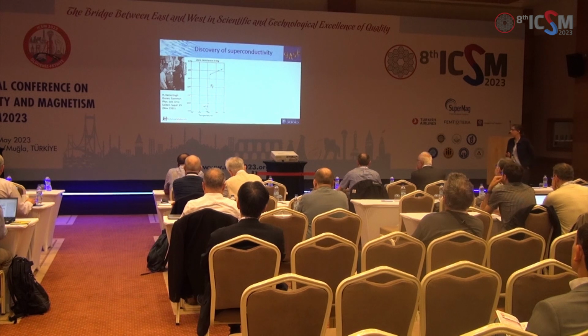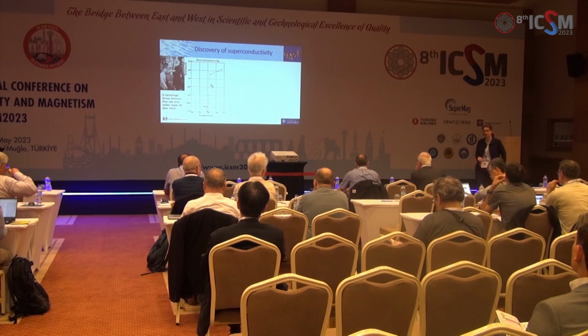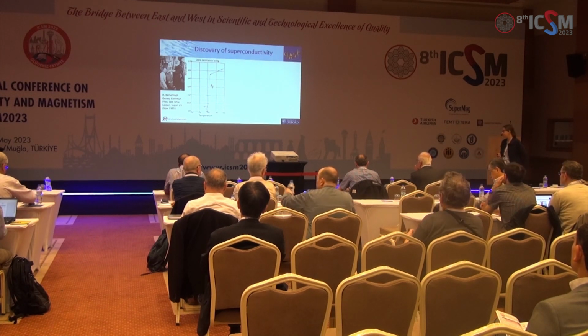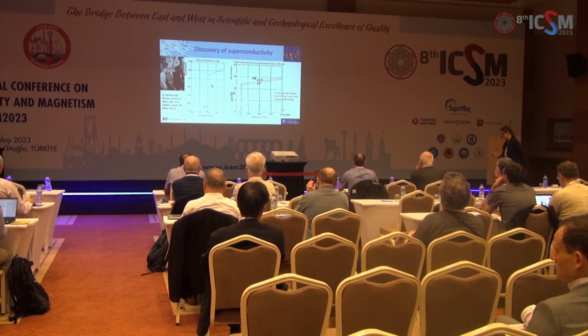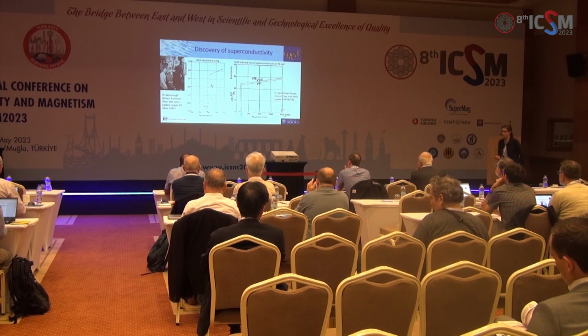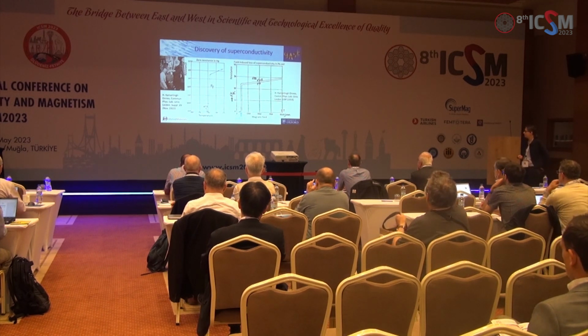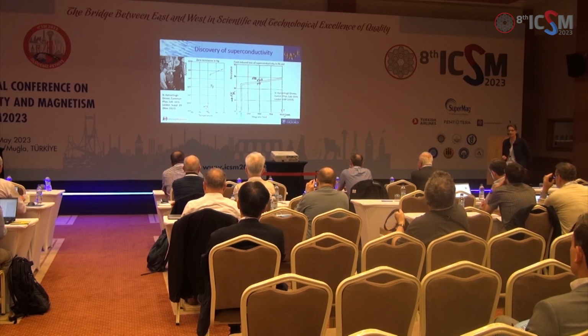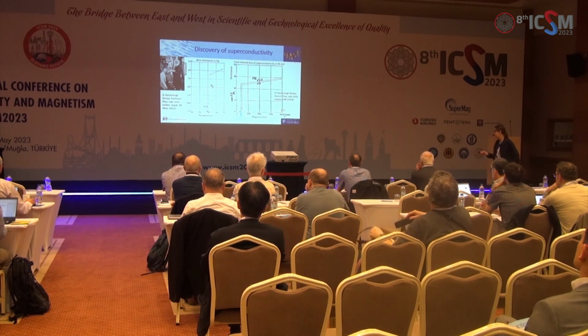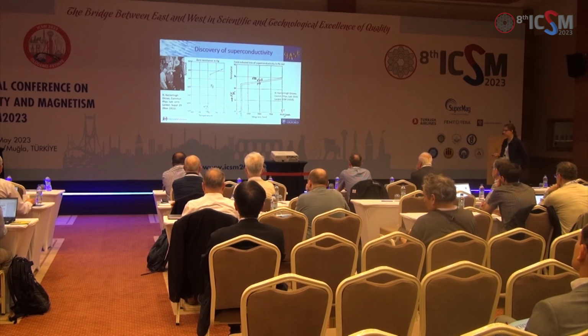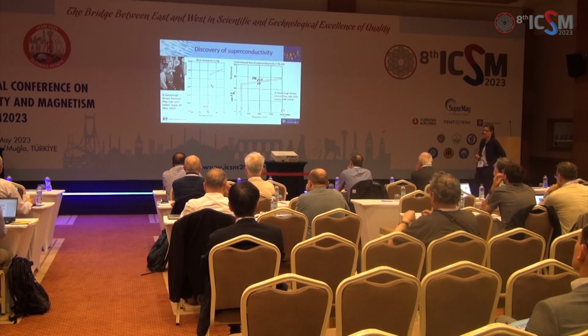So we all know about the discovery of superconductivity by Onnes in 1911, but he very quickly, after discovering superconductors, realized that one of their potential applications might be in generating high magnetic fields. But he was very disappointed a few years later when he tried this out and discovered that the kind of superconductors he was working on, the elemental superconductors, really didn't stay superconducting in very high magnetic fields at all. So here for lead, he found that about 0.1 of a Tesla was enough to stop it superconducting.